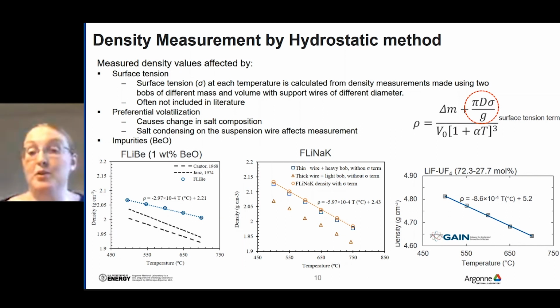And we found that to be the most accurate way to quality assure the density values. Some other things to watch out for are preferential volatilization. Density measurements in particular take a long time, and if you have one constituent slowly volatilizing off, by the end of your test, you can be measuring a different salt than you intended. So that's something to watch for. Also, that salt can recondense on the suspension wire and affect the measurement in a dramatic way.